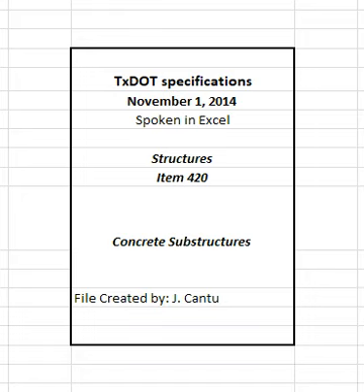4.7.16 Placing concrete in box culverts. Allow between 1 and 2 hours to elapse where the top slab and walls are placed monolithically in culverts more than 4 feet in clear height before placing the top slab to allow for settlement and shrinkage in the wall concrete. Accurately finish the footing slab at the proper time to provide a smooth uniform surface. Finish top slabs that carry direct traffic as specified in item 422, concrete superstructures. Give top slabs of fill-type culverts a float finish.